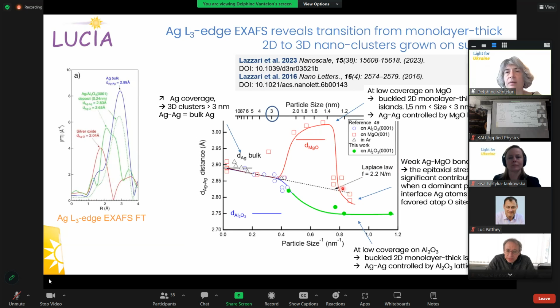They form monolayers, and the Ag-Ag distances in the cluster are determined by the lattice of the support. Here, magnesium oxide, and here, aluminium oxide. With the magnesium oxide, for very low deposit, there is a weak bonding that allows the constraint to be removed. And then above 3 nanometers, the silver coverage is high enough to allow the formation of 3D clusters in which the Ag-Ag distances are the ones of bulk silver. Voilà. I have finished the quick overview of the examples of science we can perform on the line.